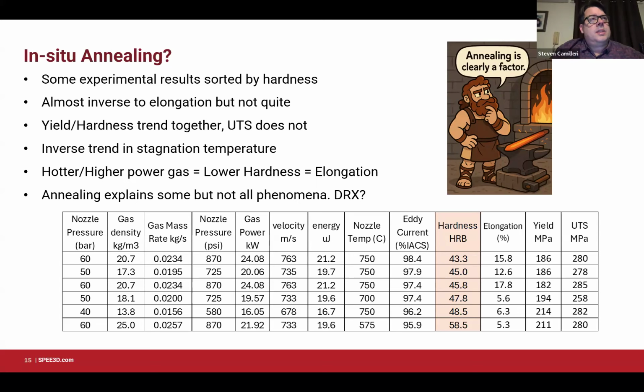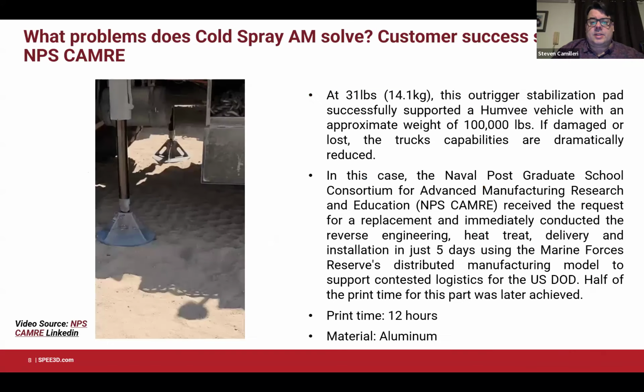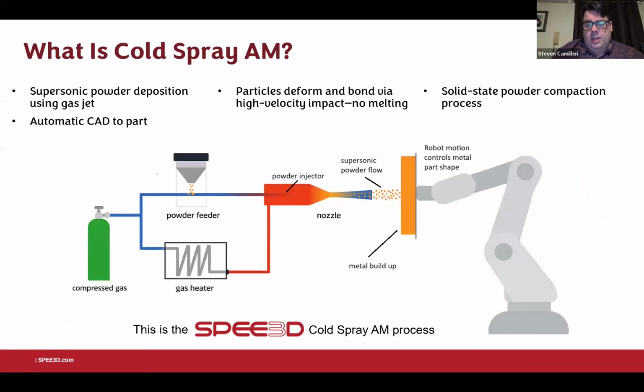So this is a deeply philosophical question, which I really like. We've been thinking about this a lot. Powder metallurgy is a process of taking a powder and turning it into a compacted specimen of some sort, and then usually sintering it to form a material and a shape. So indeed, in the process we've described here, we compact the powder using a cold spray nozzle and a robot, and then we take that compact off and we heat treat it.